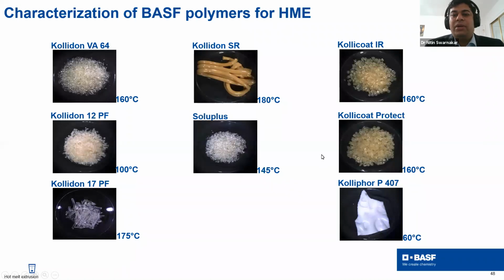And pretty much the same with Kollicoat IR and Kollicoat Protect. Generally, they are good up to 160. If you increase the temperature, they are not very good. In the case of P407, which has a very low melting point, around 60 degrees centigrade, they are melted. So extrusion and chopping is difficult. Once the material comes out, you're not going to be able to cool it in time, and then it's going to be a problem.